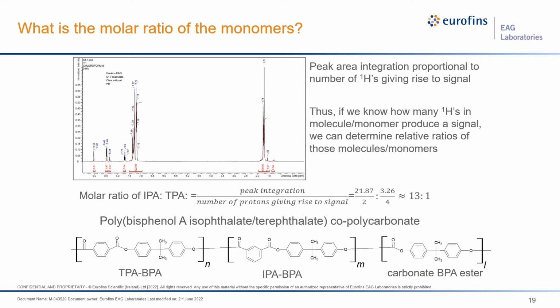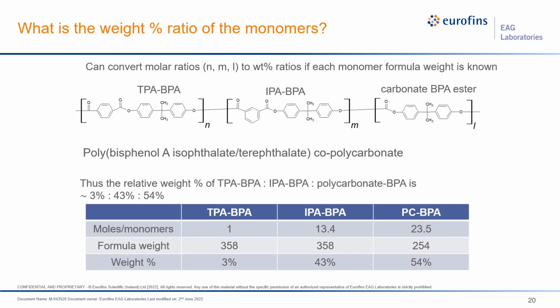We can perform a similar calculation for the polycarbonate, but most people are usually used to thinking of things in terms of weight percents versus how many monomers are present relative to one another. Using the formula weights of these different monomers, we can convert the molar ratios or monomer ratios to weight percentages, which are a little bit easier for most people to understand. When we perform these calculations, we are able to conclude that this sample contains about 3% of the terephthalate, 43% of the isophthalate, and 54% of the polycarbonate.